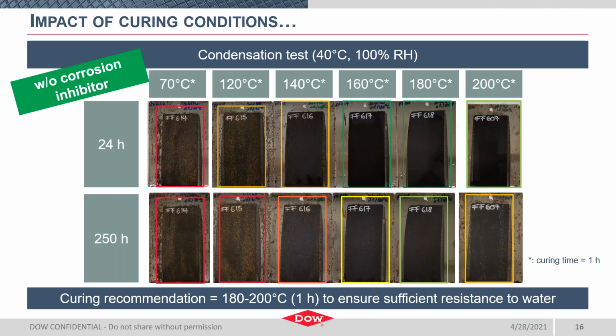Okay, looking at one more facet of cure conditions before I show other parameters that we explored to come up with our starting point formulation. Here I illustrate the impact of cure on water resistance. Panels were cured for an hour at different temperatures ranging from 70 to 200 degrees Celsius, and then put into a humidity chamber at 40 C with 100% relative humidity. The top row shows your 24-hour exposure in that chamber, and the bottom row shows 250 hours exposure.